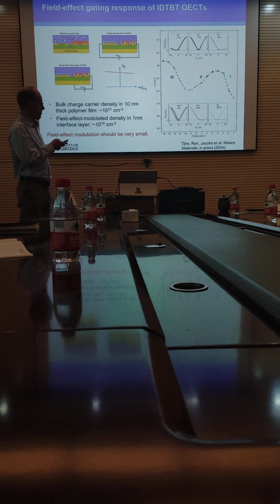We thought it would be a difficult experiment because, even if you make the polymer film very thin, you have so many charges in the bulk, and with the FET gate you just modulate a few. We estimated that you would maybe get 1% change in the current for a 10 nanometer film. So we thought it would be difficult, but worth trying. So here is what we actually saw.